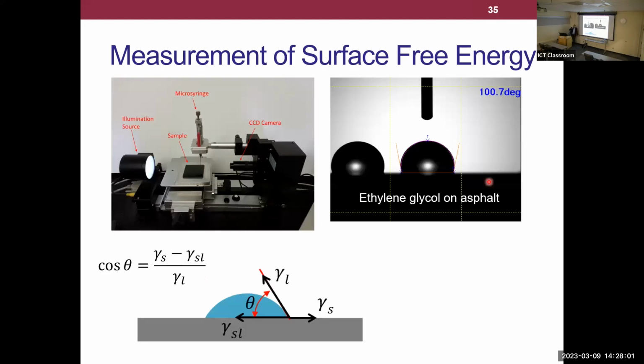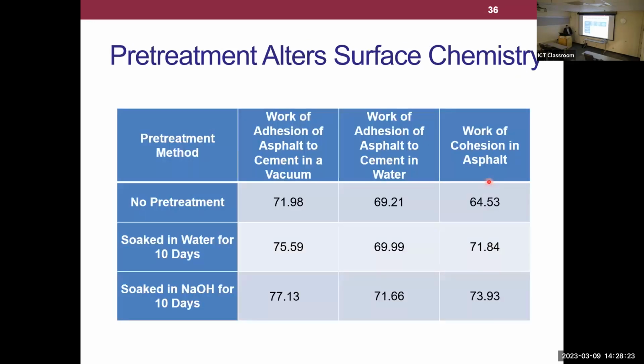And why are we seeing even more leachate after we're trying to pre-leach those organic compounds? So the next thing we tried to do was some surface energy measurements. Probably some of you are familiar with this in this lab. When I was a PhD student, I used Dr. Alcade's equipment and did some of these measurements myself. So we're also doing these measurements still. And what we found is definitely after soaking the RAP in that NaOH solution, we are somehow changing that surface chemistry. The surface free energy is changing.